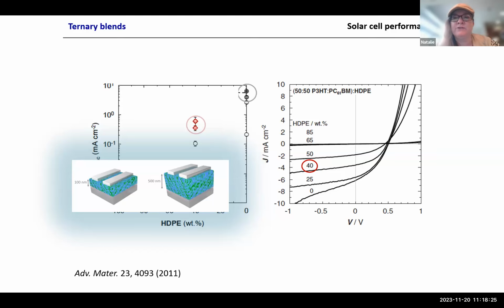I should have maybe put it in. It's a ternary phase diagram. And you see that the polyethylene, but actually that's nearly intuitive, I mean, it's carbon hydrogen. Nothing really interacts with polyethylene, only Teflon is worse in interaction. So it was not really surprising, but the phase diagram definitely shows it's really just sitting there and helps with mechanical robustness, reducing traps, because we really think it prevents humidity from going in, but it doesn't affect the ordering. Therefore, the processing is so important. Absolutely. You really have to have the P3HT, PCBM essentially solidify first. And that's why they sort of behave the same.